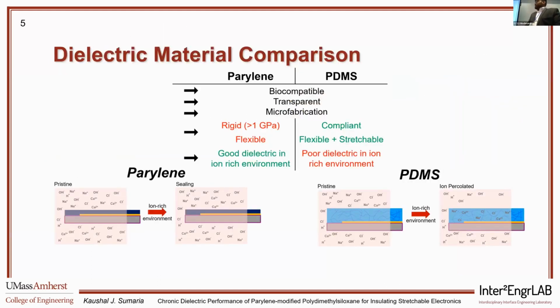So if we summarize the material properties of these two important materials used in sensors, we see two stark contrasts, one being the stiffness of the material. Another thing being that if you look at the parylene here, it can resist the diffusion of ions very well, whereas PDMS, being an elastomer, is known to allow diffusion of ions inside, and then that changes some of the material properties that are important for the sensors.